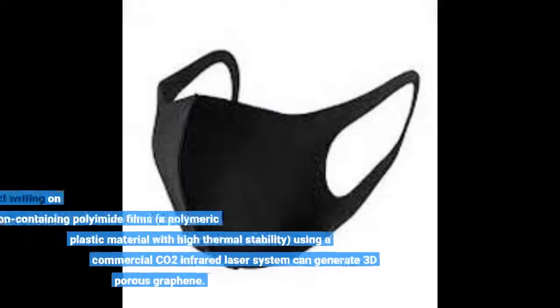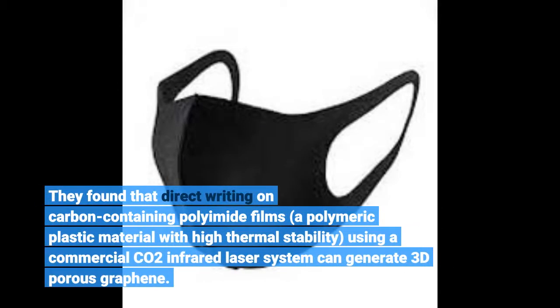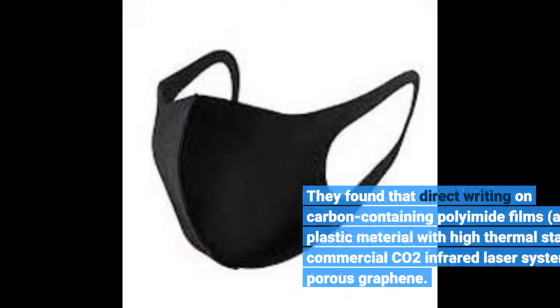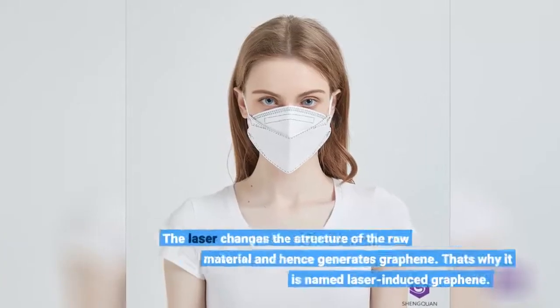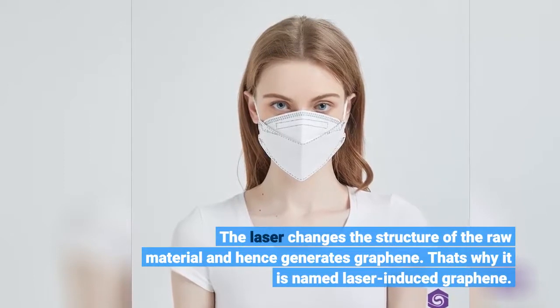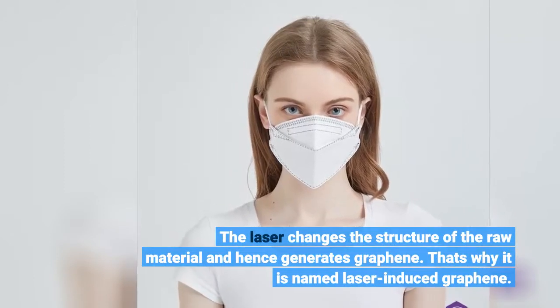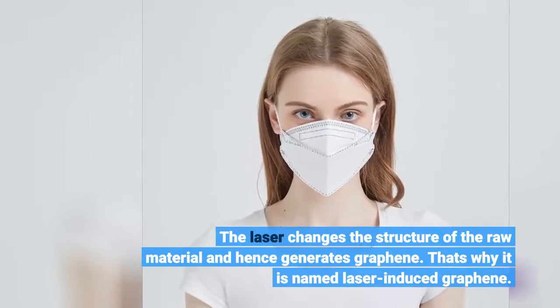They found that direct writing on carbon-containing polyimide films, a polymeric plastic material with high thermal stability, using a commercial CO2 infrared laser system can generate 3D porous graphene. The laser changes the structure of the raw material and hence generates graphene. That's why it is named laser-induced graphene.